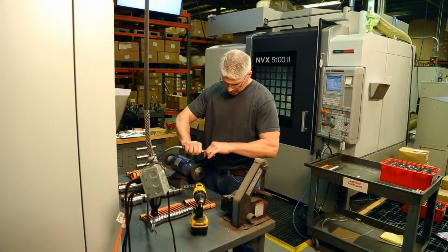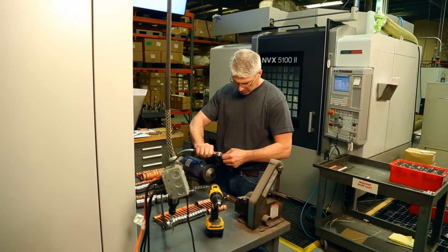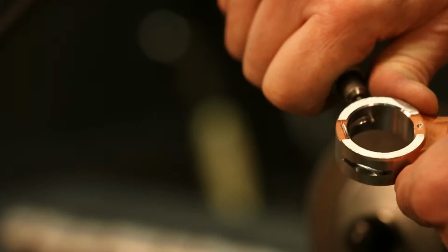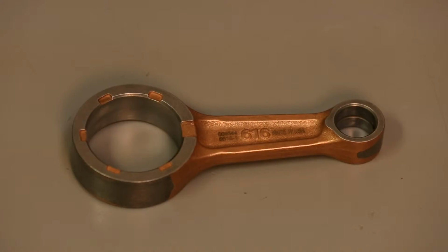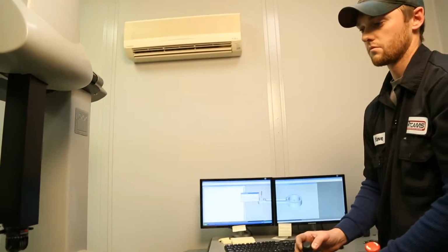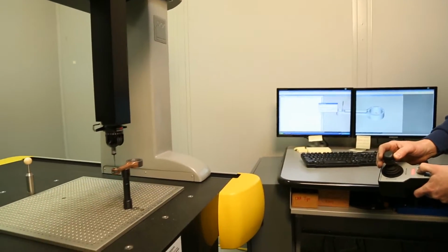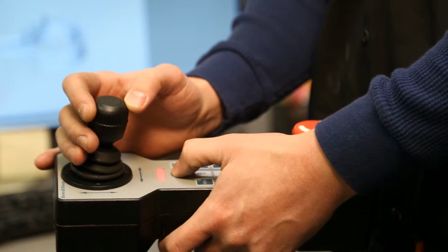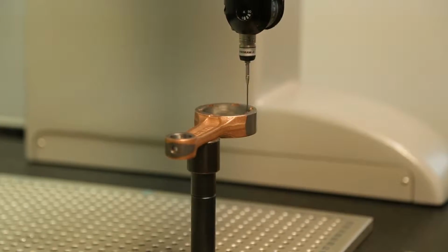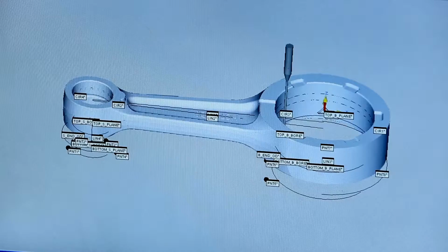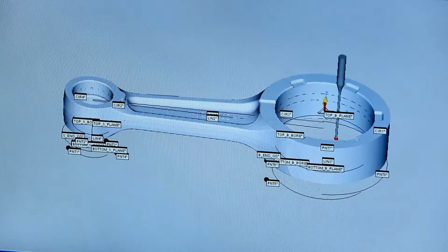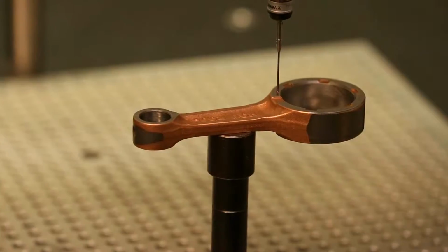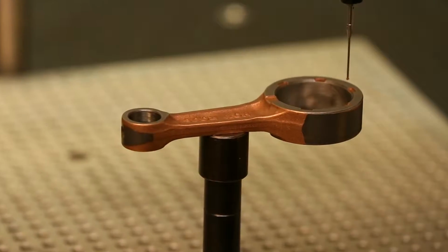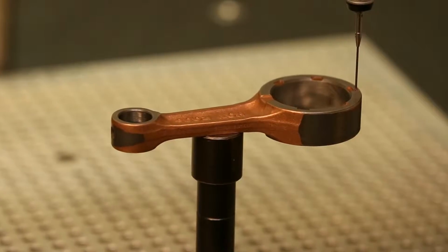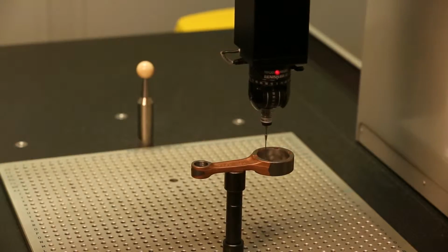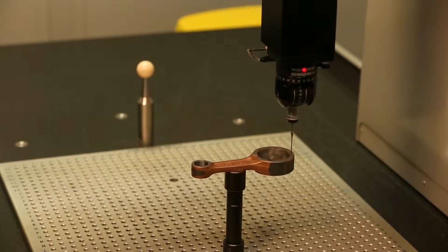While the mill operator inspects the rods by hand throughout his production run, at the beginning of each new production batch and the start of each new shift, 1 rod from each fixture station in the mill, 3 total, are sent back to the Quality Control Department for inspection on the coordinate measuring machine. The CMM operator inspects all of the critical dimensions of the rod. This includes the center-to-center of bearing holes, the overall length, the individual diameters of the rod bearing and wrist pin bores, the overall width of the rod at each end, and checks for parallelism and any twist of the rod. This thorough inspection ensures that each mill is set up and operating correctly.